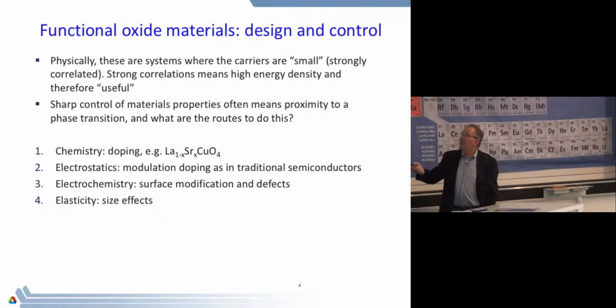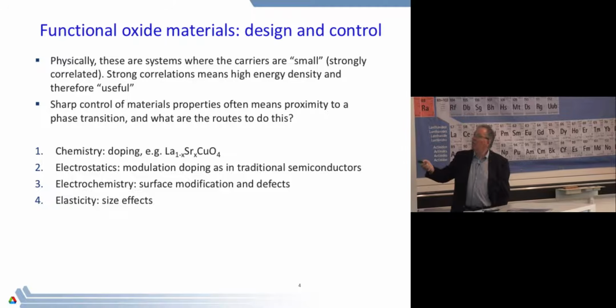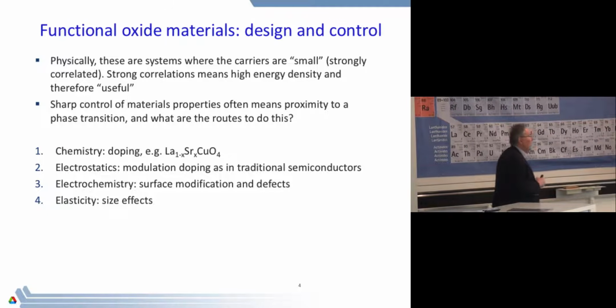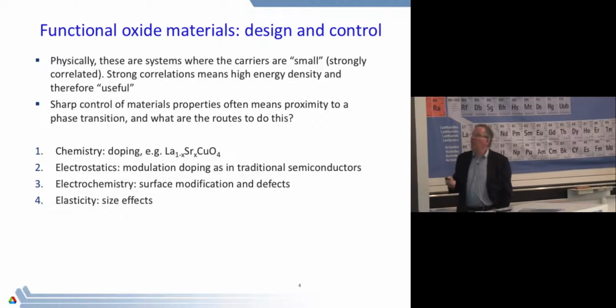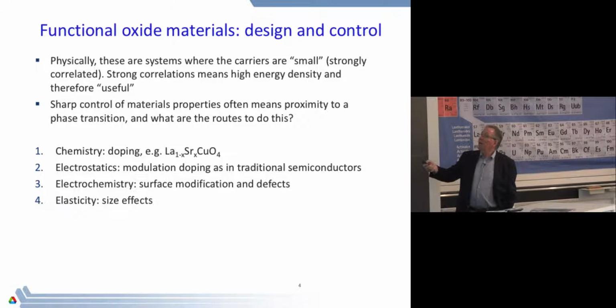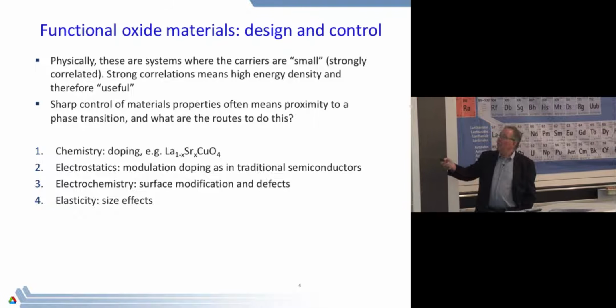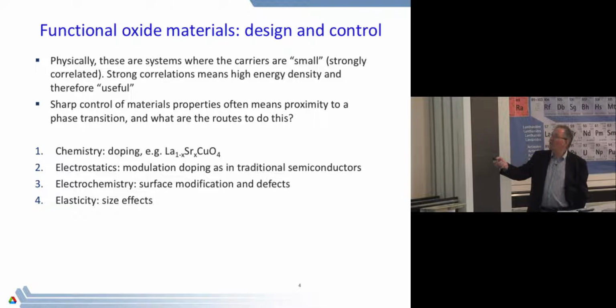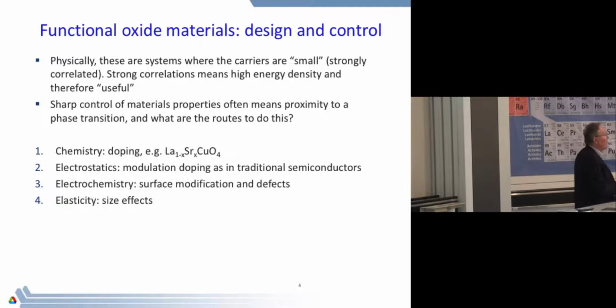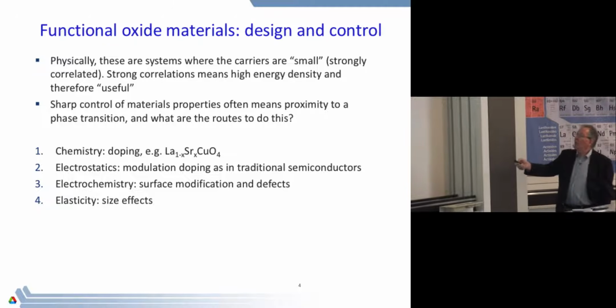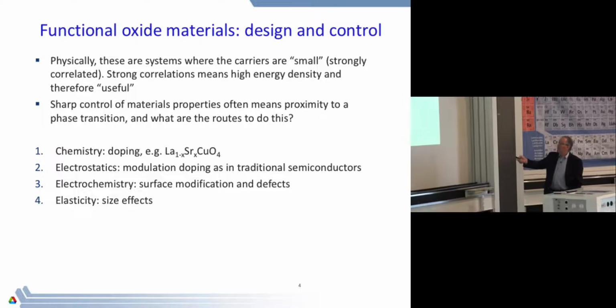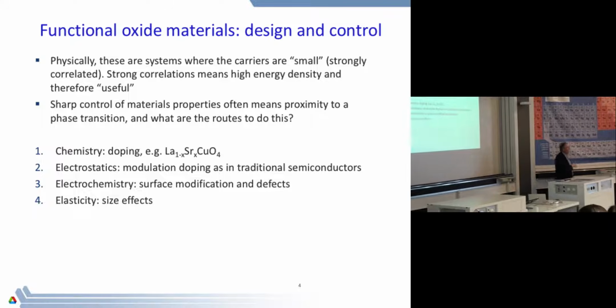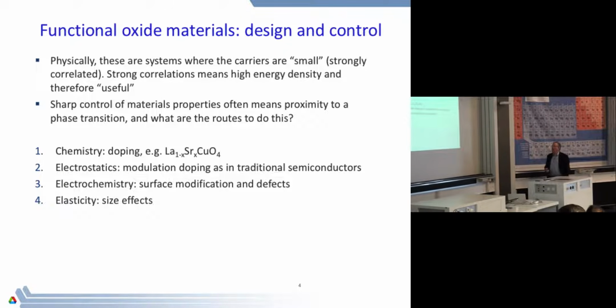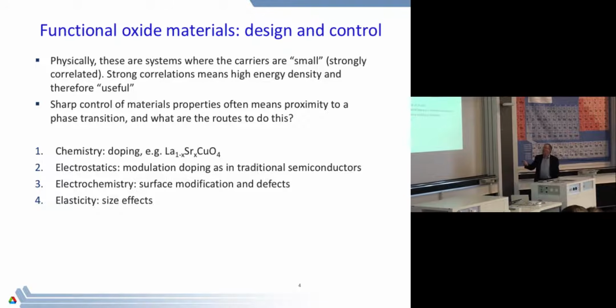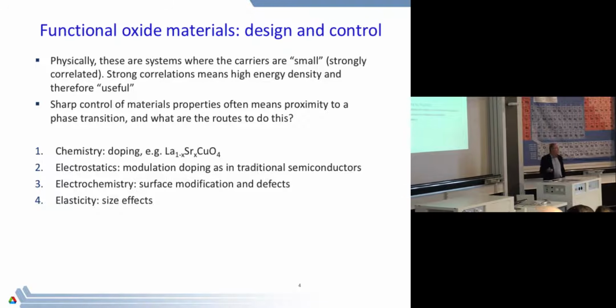Well, there's a classic one that you may be familiar with in the cuprates. So lanthanum strontium cuprate is the first of the series of high temperature cuprate superconductors. And again, what you're doing in something like this is that you're changing the carrier density. So strontium is 2+, lanthanum is 3+. So as you change x in here, you're changing the number of electrons that sit in these copper oxide planes. Okay? But you can do different kinds of things.